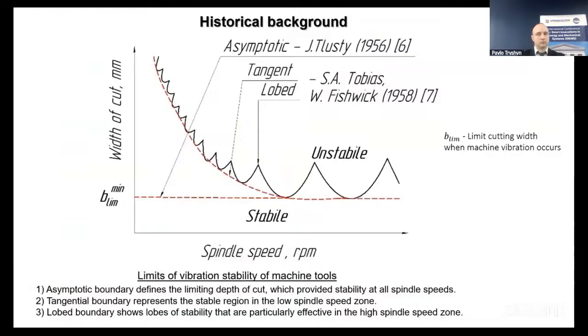In the works of the founders of the theory of regenerative vibrations, Tlusty, Tobias, Merritt, the limits of vibration stability of machine tools were defined using the limiting width of cut and machine spindle speed. First, the asymptotic boundary defines the limiting depth of cut which provides stability at all spindle speeds. Second, the tangential boundary represents the stable region in the low spindle speed zone. Third, the lobed boundary shows lobes of stability that are particularly effective in a high spindle speed zone.